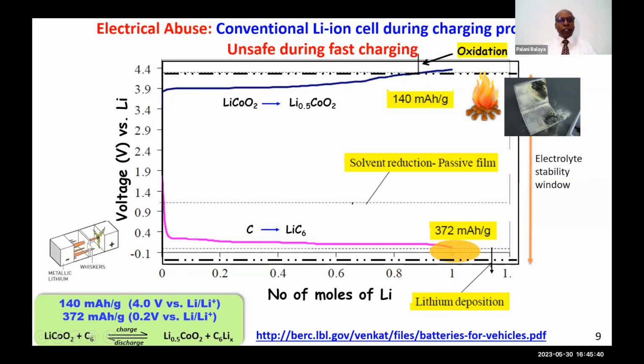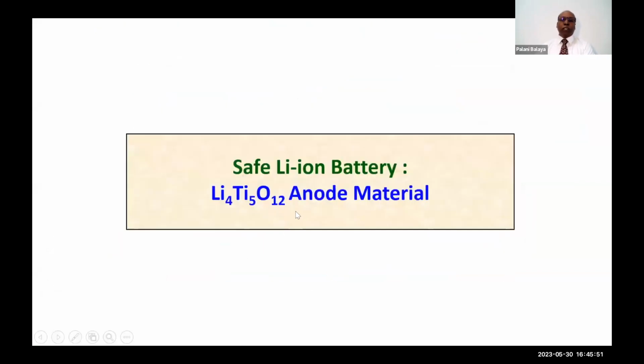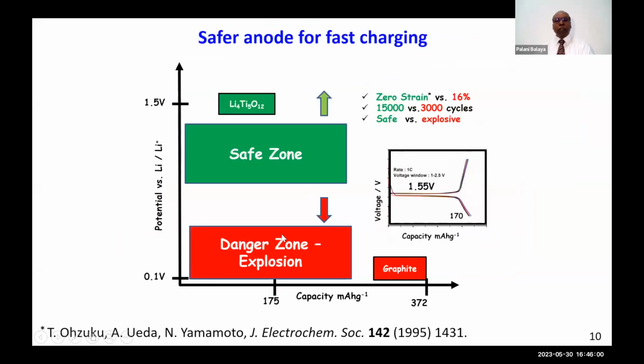This leads to so-called dendritic lithium deposition on the graphite, which causes shorting, internal micro shorts. So one should not do fast charging. So now that's a form of electrical abuse. Now the question is, is there a way to come out of this? Yes, lithium titanate is a technology for fast charging and fast discharging. It's a safe technology, well-established technology. So you can see here, the lithium titanate insertion potential is far above 0 volt. So you can insert quickly, extract quickly. Whereas for graphite, the red color is the danger zone, you have to insert slowly, but extraction can be quick. And interestingly, this technology is well known. Lithium titanate is zero strain and has a long cycle life. It is extremely safe, etc., etc.